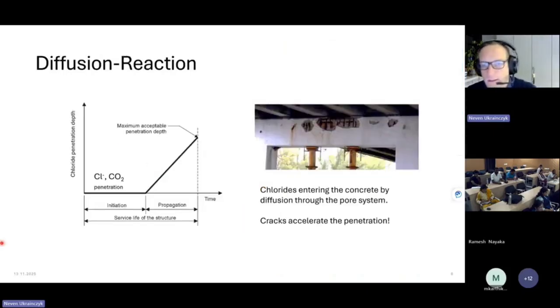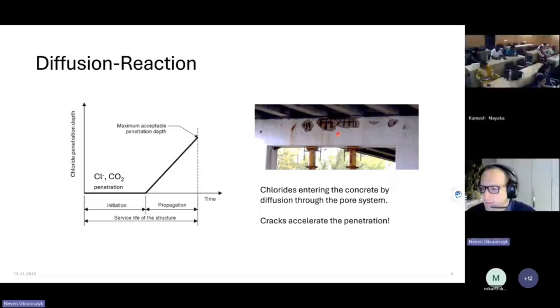So back to the theory. This is a diffusion reaction problem, because the chlorides are diffusing through the cover depth, through the pore system of the concrete. Of course the cracks accelerate the penetration, but the more steel corrosion you have, the bigger the volume expansion and the more cracks, and then at the end you have the spalling effect. This is typical spalling, but at least then you can see where the damage is. The most critical is when you don't see the damage, but inside the steel bar is corroding.